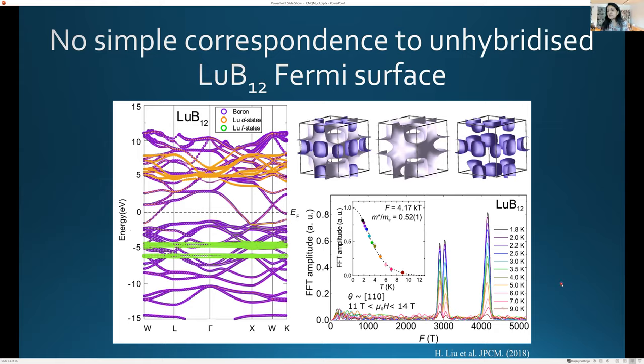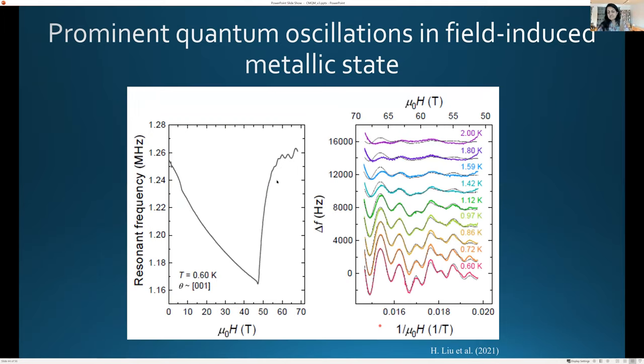So it seems like maybe there's a different mechanism that's giving the Fermi surface in this case, because it's giving you a small, heavy Fermi surface, not a large light Fermi surface corresponding to a conduction electron surface. In the case of the YbB12, it does get metallized above 50 Tesla.